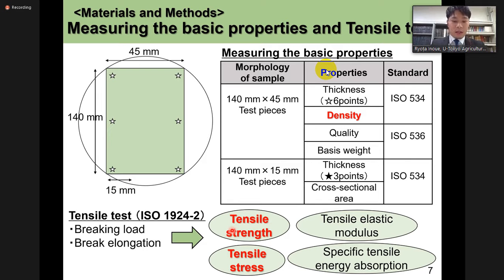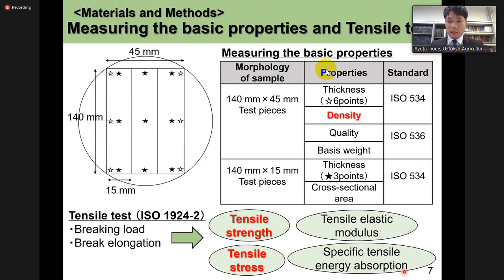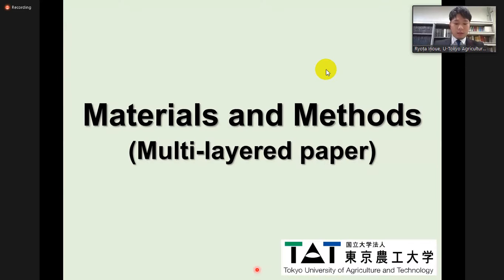The 6 white star marks are where the thickness was measured. Next, we cut the test pieces into 140 millimeters by 15 millimeters test pieces. We measured thickness and calculated the cross-sectional area. The 3 black star marks are where the thickness was measured. We performed a tensile test using these test pieces. The tensile test gave breaking load and break elongation values. We calculated the tensile strength, tensile stress, tensile elastic modulus, and specific tensile energy absorption from those values. In this presentation, for the sake of time, I'll talk only about the density, tensile strength, and tensile stress measurement results. Next, I'd like to talk about the multi-layered paper.